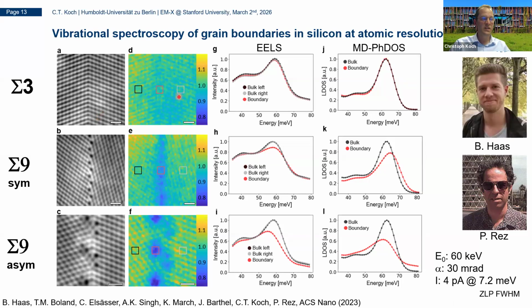That is the map he got. You can still see the atomic columns, but you can also see there is no contrast going from the left grain to the right grain across this grain boundary. So the grain boundary is hardly visible. You can see the atomic columns and the structure, but the spectra don't change. These are three different spectra, one from the left-hand side, one from the middle, and one from the right-hand side, which all look the same in the experimental spectra. And what I've done is I've built an atomic structure that has exactly these dumbbell positions in it, and also this grain boundary. We gave it to the group of Peter Rez and Tara Boland at Arizona State University, and they did some MD calculations and extracted the phonon density of states, and they were also not able to see any difference.